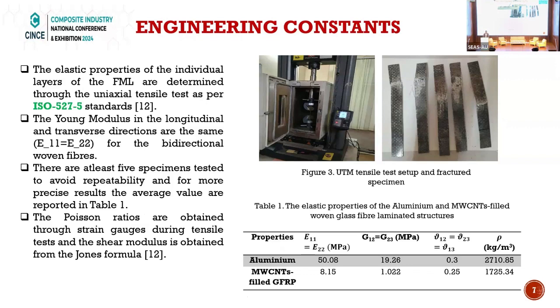To get accurate results and minimize error, I tested 5 samples in the length direction and the 45-degree direction. The 45-degree fiber direction elastic property is required to calculate the shear modulus, which is calculated through the Jones formula, already mentioned in Robert M. Jones' Mechanics of Composite Materials book. After performing the tensile test, elastic properties are shown in table 1. These properties are further used to perform numerical simulation in finite element software.